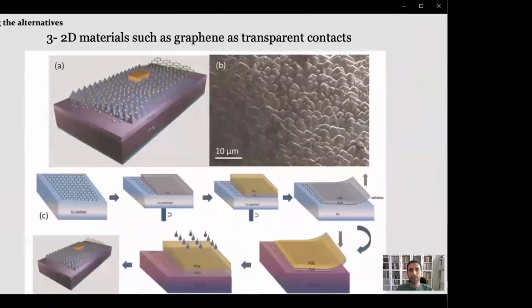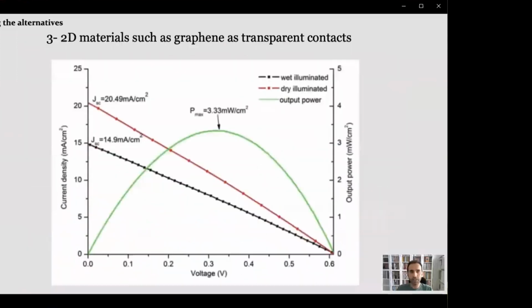So another option to tackle this silver problem is to use 2D materials, such as graphene as a transparent contact. A new dry transfer method of graphene as transparent electrodes in textured silicon solar cell was recently reported by Yuan Zheng and his group in China. Even though it sounds great to have nothing on the front surface, considering graphene is transparent up to 95%, the technology is promising, but it needs to be developed. As you see, the current density is suffering due to the lack of carrier collection.